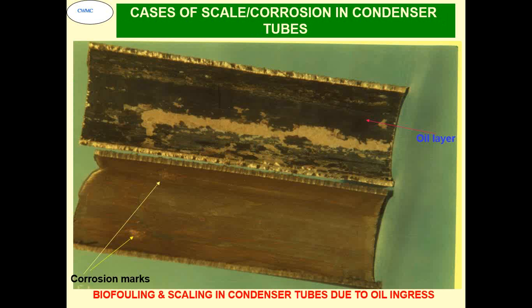Now this was a typical case where the water was supposed to be corrosive in nature, but all of a sudden the plant reported they had 1 mm thick calcium carbonate scaling. When we analyzed the problem, we found there was a black layer, what you see on the top tube, that was caused because of the oil in the water. So oil formed a film that changed the heat transfer characteristics, and the water which was supposed to be corrosive in nature, even with that low scaling tendency, a heavy scale had formed in a short while. So the outcome is we have to ensure that no oil comes into the cooling water system.